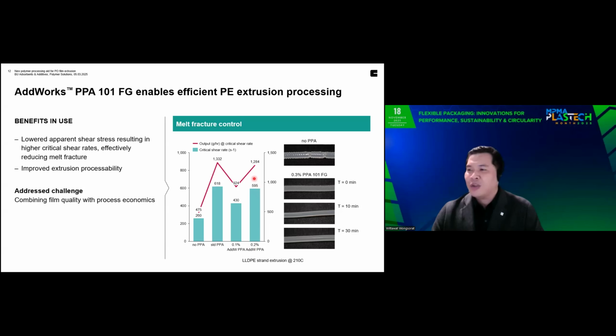However, when the method to check critical shear rate is different, the critical shear rate result is also different. We found that some customers use a capillary rheometer, while some customers check the real critical shear rate at the wall during real extrusion. So we recommend customers also check surface smoothness, because sometimes if the customer uses a capillary rheometer, they may find that the critical shear rate is not at the same level as PPA. But in the real process, we can find the surface smoothness is there.